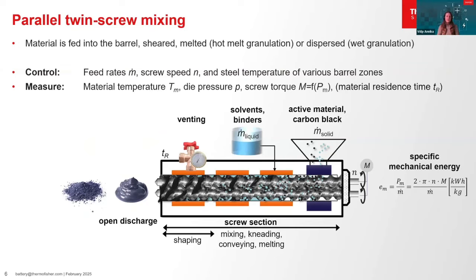Because extrusion is defined as shaping material by pushing it through a die, we speak of a twin screw mixer when no die applies. With such a twin screw mixing setup, battery materials can be mixed with and without the use of solvents. The mechanical and the thermal energy input in the material is defined by the screw design, the screw speed, the feed rates, and the mixer temperature. No pressure is applied to the material. It is conveyed without any constriction out of the mixer and collected in a container. Twin screw mixers can be applied at several points in the battery manufacturing workflow, as shown on the next slide.